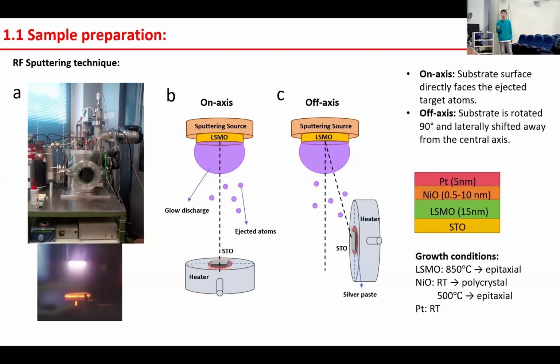In this case, we utilize on-axis and off-axis geometries. In the on-axis, the substrate faces the target, and in the off-axis, the substrate is rotated by 90 degrees and moved forward a little bit from the central axis. And the material is grown as three layers: LSMO, nickel oxide, and platinum heterostructures, where the corresponding thicknesses are as shown in these figures.